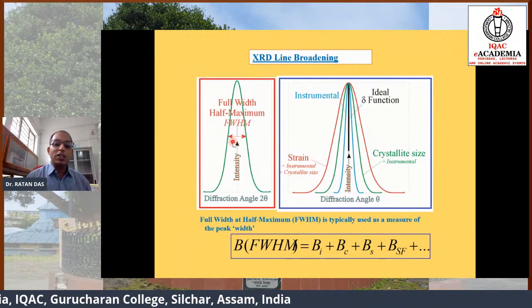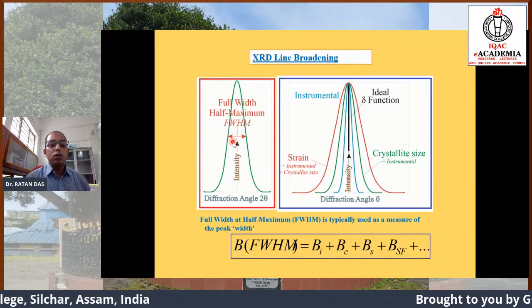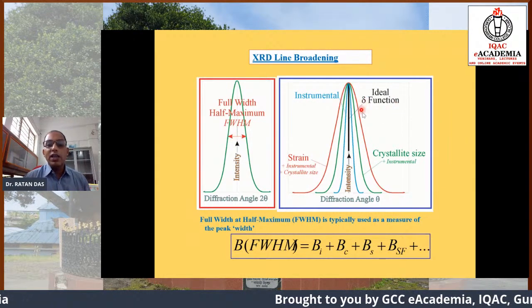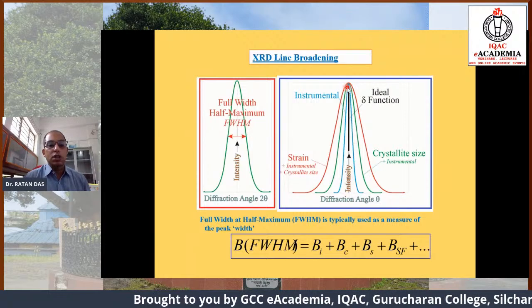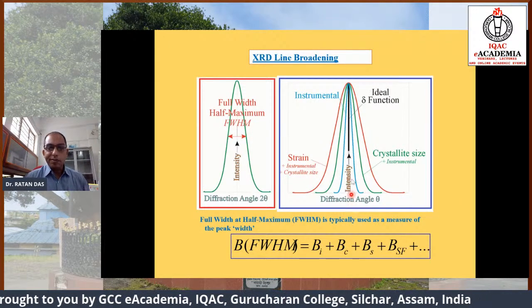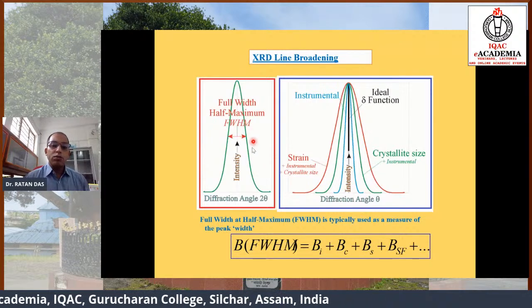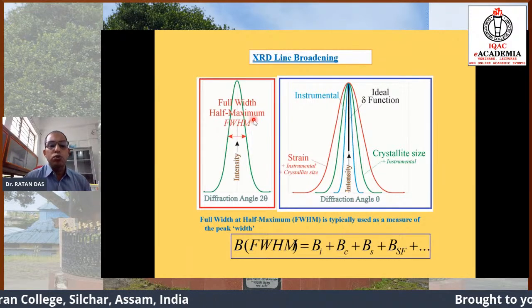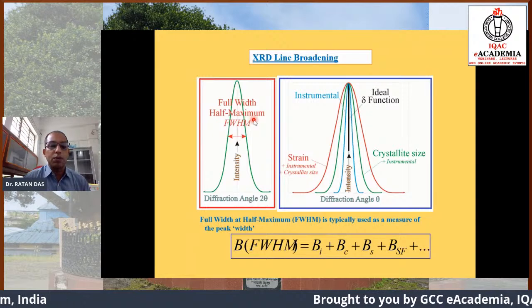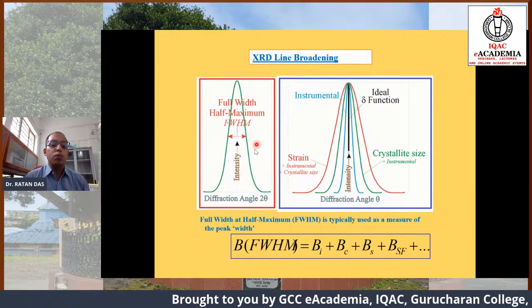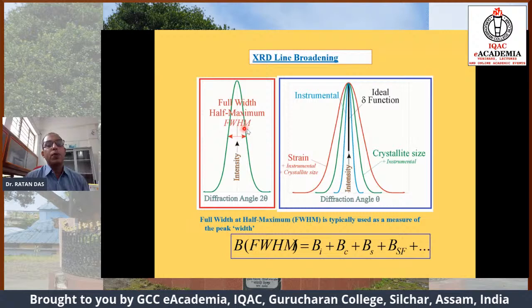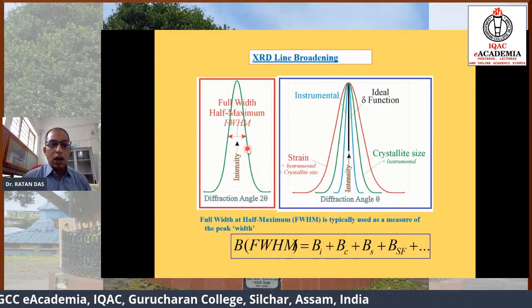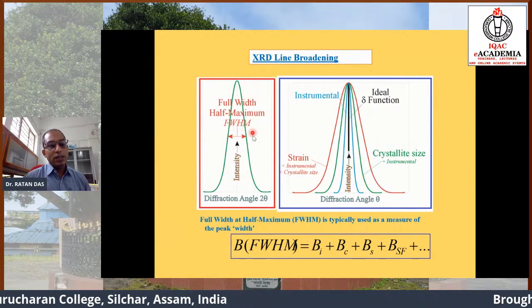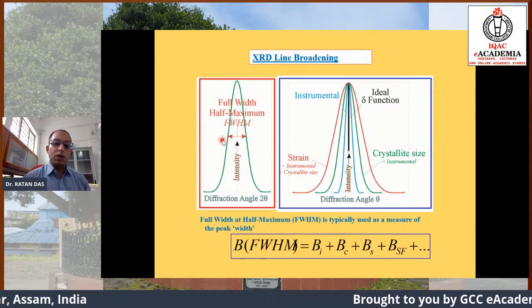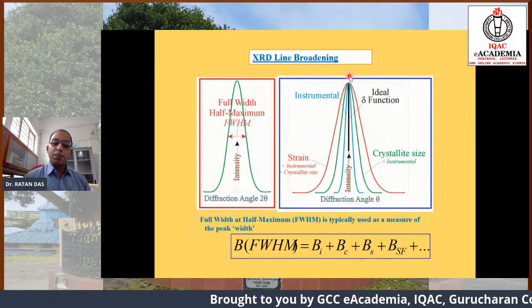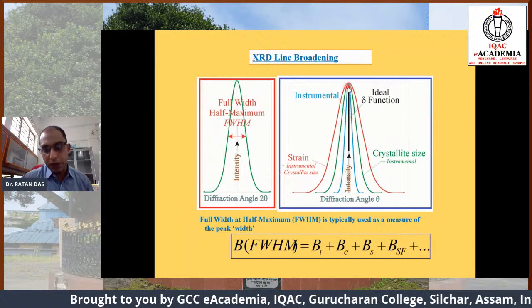Okay, so for a bulk sample, it is very infinite in size. So we generally obtain the ideal delta function with no width. Again, I want to tell you that this is very important for the beginners. Those who know, it is very simple for them. But those who do not know, this is very important, because full width at half maxima plays a very big role. Smaller the size, higher is the full width at half maxima. Higher the size, lower the full width at half maxima. Bulk sample shows the infinitely peaked diffraction pattern with almost no width.